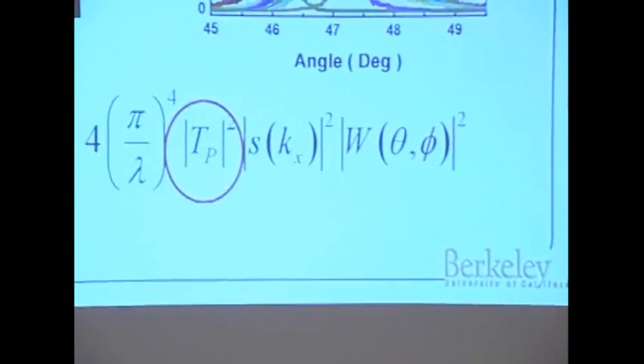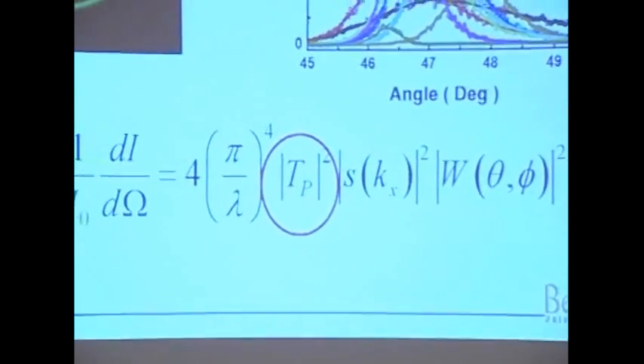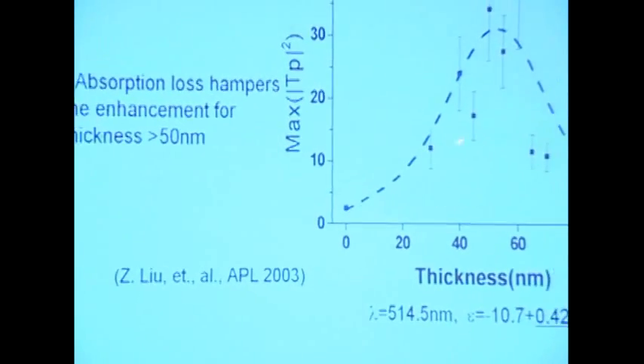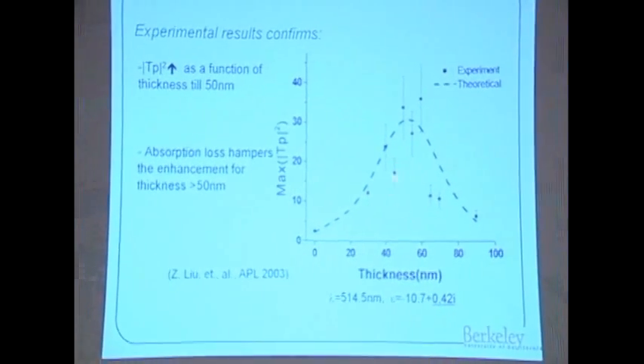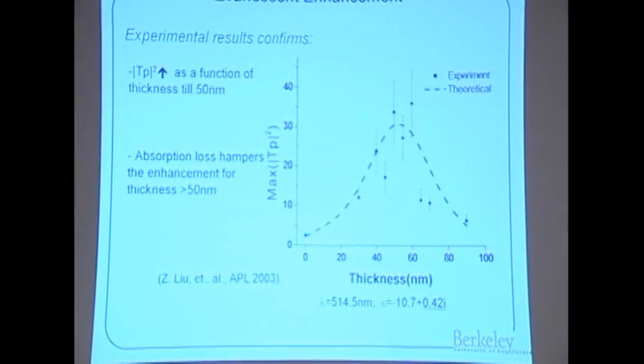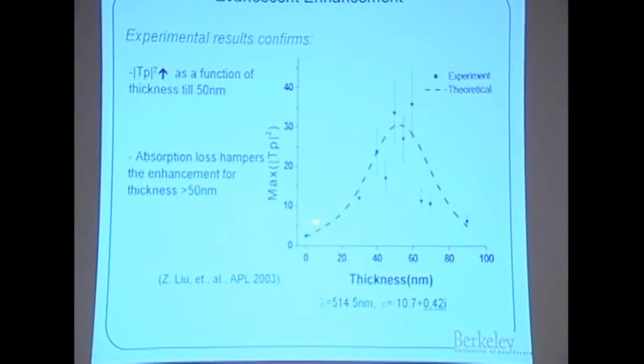And this dipole function can be calculated. This takes care of the polarization orientations in theta and phi. So essentially, we can determine this because we know the wavelengths, we know this from the AFM measurement of the surface roughness, and we know the scattering of the plasmon. So this is the final result. And these dotted numbers are experimental values, and this blue line is the theory.